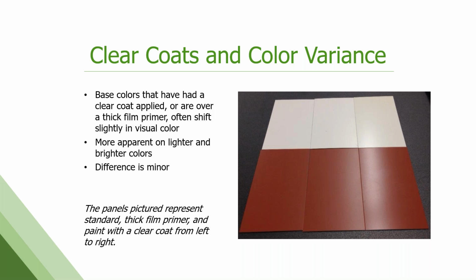So on lighter colors, an example here, you can see from left to right is no clear coat, and then with a high build primer, which can also affect color, and then with a high build primer and a clear coat, you can see that lighter color shifts yellow a little bit visually, but the medium and darker colors, you can't really perceive it. So just a caution, if you're going to do a job that needs a clear coat, understand that it might shift the color a little bit, and that can be overcome with a reformulation of the color coat underneath in a lot of cases.